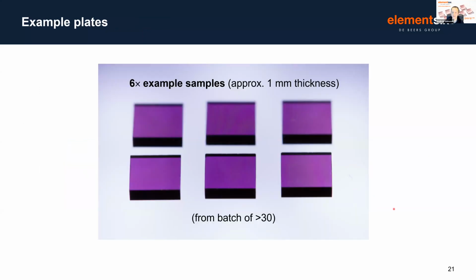So I want to just briefly show you what these samples look like, because they're quite nice looking. One of the byproducts of improving and reducing the amount of parasitic defects is that we have a more vivid color, and this vivid purple color that you can see only comes about because of the few parts per million concentration of NV centers, and comparatively high concentration compared to what we were talking about at the start of this presentation, where we were literally just talking about one NV center. It is those NV centers that give that very characteristic and very pleasant purple color. So this is just a photo that I took of 6 example samples that are around 1 millimeter in thickness, around 3 to 4 millimeters laterally, from a batch of samples in excess of 30 that we produced.